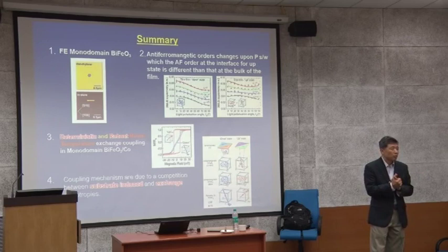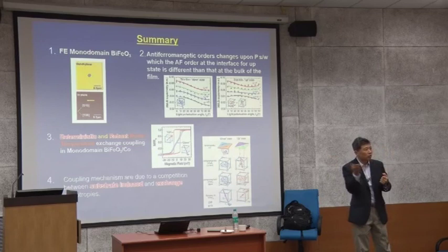So here, one possibility is that maybe in a monolayer region at the surface, there is a possibility of sucking oxygen from bismuth ferrite. Cobalt is not as reactive as titanium, and hopefully we don't have that issue. At room temperature, the kinetic energy is so low, so we believe that the surface is relatively sharp.